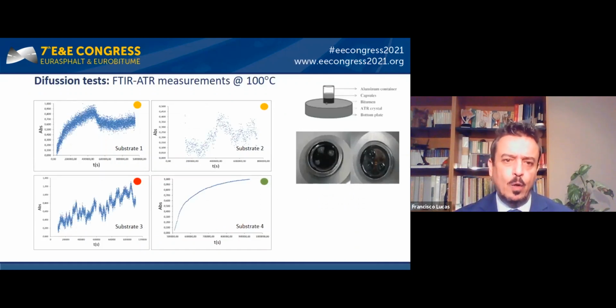In the next slides, we analyze the diffusion of the rejuvenating agent in the different substrates by means of the FTIR diffusion test at 100 degrees, which provides us with information about the percentage of absorption by the bituminous matrix of the rejuvenator at the indicated temperature. It's not a test designed specifically for this type of material, but it seemed appropriate to consider it. We see that for substrate 3, the curve shows strange results, and that for substrate 4, the diffusion in time is perfect. However, we have decided to stay in the analysis with substrates 1 and 2 because although the method does not perfectly reflect diffusion, their high impregnation capacity has led us to choose them.